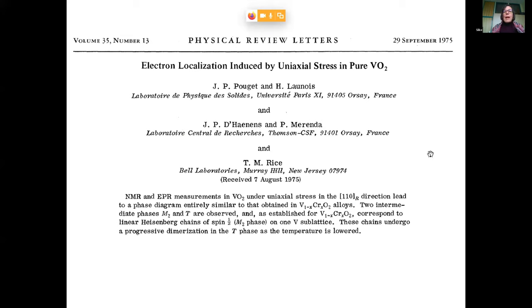Okay, strong counterarguments against the idea that everything might just be a Peierls transition came from the experimental side, from Maurice Rice, and here the first author is Jean-Paul Pouget, I think it was his thesis work. What they did was to make little variations of VO2 by either slight chromium doping or tiny uniaxial pressure. Under these conditions, they could stabilize further phases of the material, in particular phases where you would have two inequivalent chains in the unit cell, of which one would only be dimerized but not tilted, and the other one would be tilted but not moving closer together.